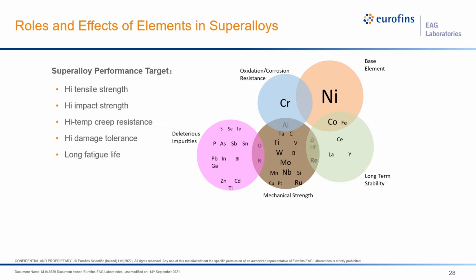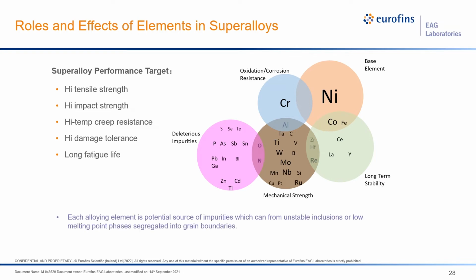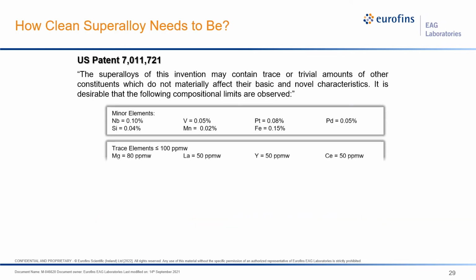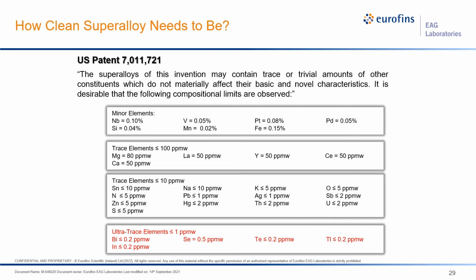They are either low melting point phase forming elements, or they can form other impurities which are particularly harmful, including sulfur, selenium, tellurium, lead, and bismuth, even at sub-ppm levels. To give you an example, here is a US patent, which clearly shows how clean superalloys need to be, from tens or hundreds of ppm level, to less than 100 ppm elements, to less than 10 ppm elements, and to those ultra trace level elements. See how low it has to be controlled.